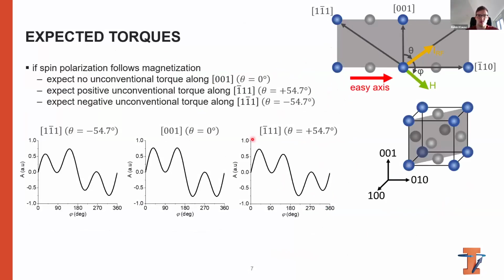So what do we expect if the spin polarization follows the magnetization? We set the magnetization to be along the magnetic easy axis, the 1 bar 1 0 direction. If we apply a current along the 0 0 1 direction, which we say is theta equals 0 degrees, we expect only conventional torques because the spin polarization would be perpendicular to the current along the easy axis, which is the conventional case.